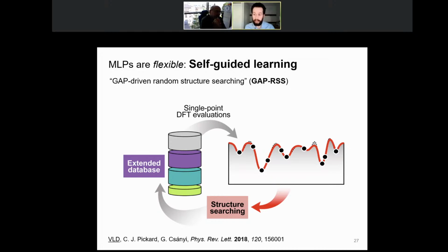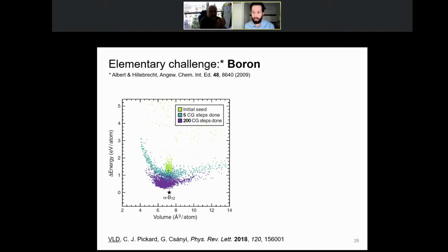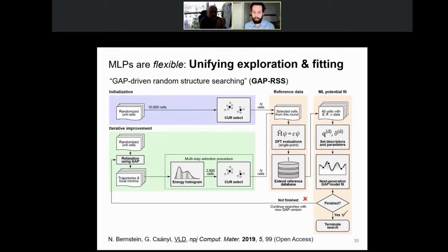So it is important how you do the sampling at the beginning. So how you choose those points which are higher up on the potential energy surface. And some of these approximations that we use in the search are really, as in Chris Pickard's and Richard Needs' AIRSS approach, where you say, for example, you're going to use a hard sphere cutoff. You're not going to place two atoms extremely close to each other. You put some reasonable constraints and you use some symmetry. And in fact, Noam's code makes use of many of these reasonable approximations.